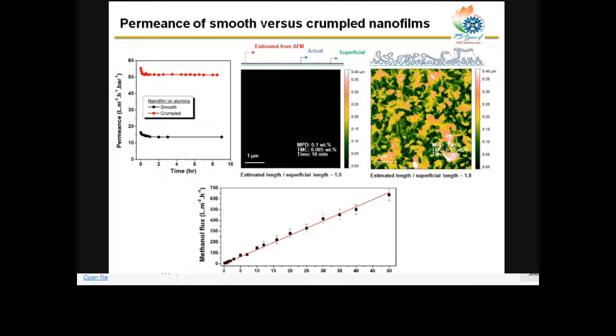Again, if you look at the permeance on the left, you can see the permeance of the smooth film, the black curve on the bottom, is much lower compared to the crumpled nanofilm, because, as I said, the crumpled structure will have a much higher permeable area compared to the smooth film. The two AFM images show that the smooth film is basically a dark background, and the crumpled film, which you can see on the right in a greenish color, clearly shows the rough crumpled structure of the nanofilm.